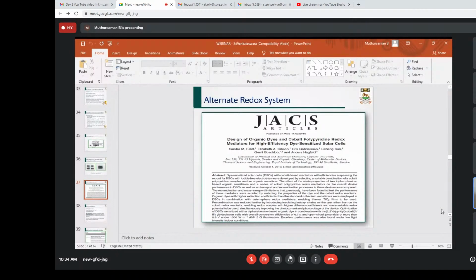So then we looked for an alternate redox couple. The Hagfeldt group from Uppsala first made a cobalt electrolyte. They replaced the iodine redox couple with cobalt. The first time they got 6.7% efficiency, also with good stability. This was achieved through adjusting the band gap of the dye to match the electrolyte. They used a new dye also, D35.